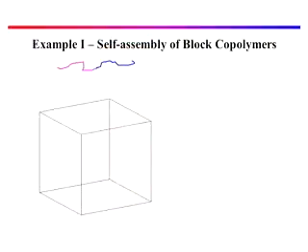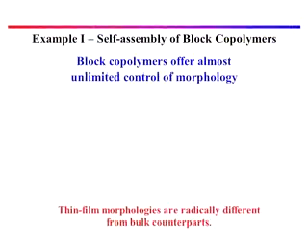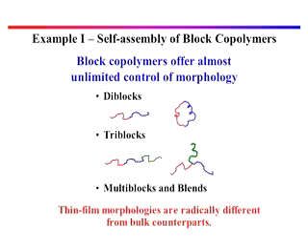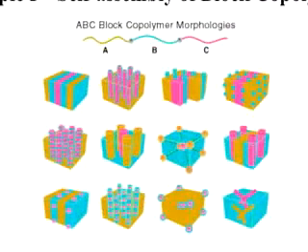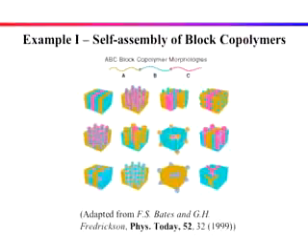One ongoing project in my group is to map out the phase behavior of confined block copolymers. These materials can self-assemble into periodic structures at nanometer scales, and therefore have lots of applications in nanotechnology. Here is a Monte Carlo simulation showing that asymmetric diblock copolymers spontaneously form hexagonally packed cylinders in bulk.